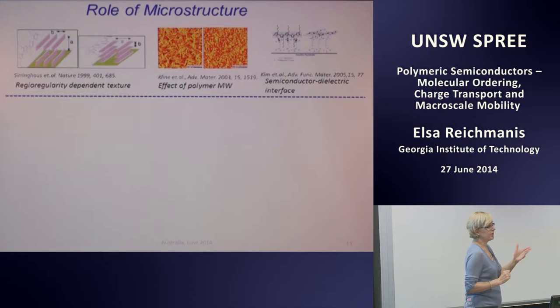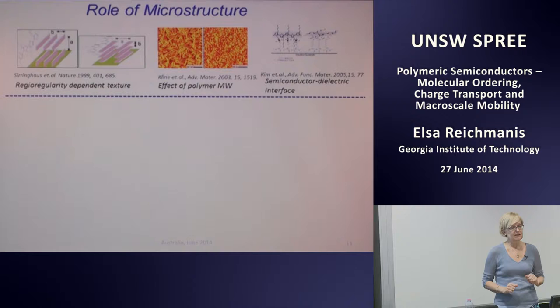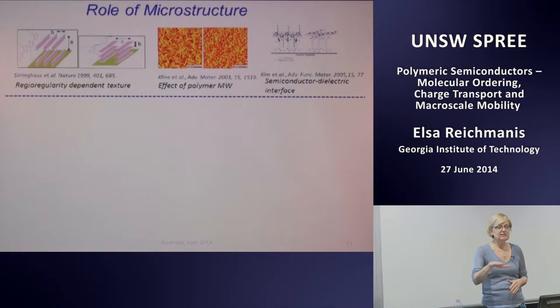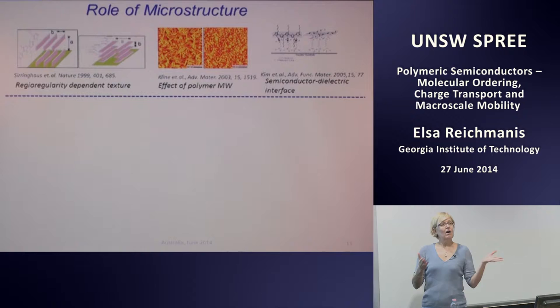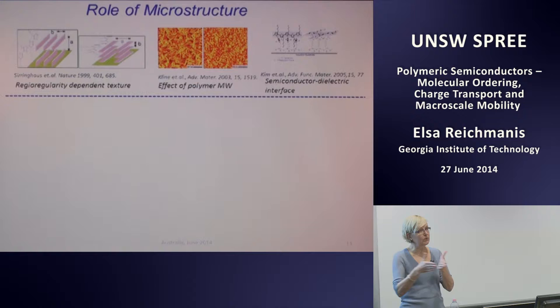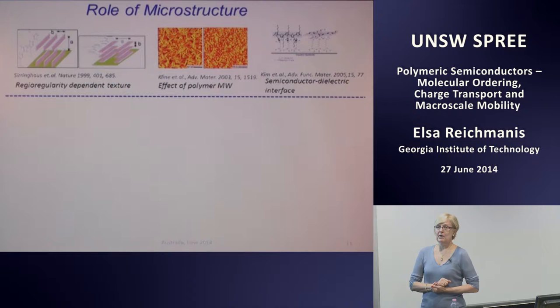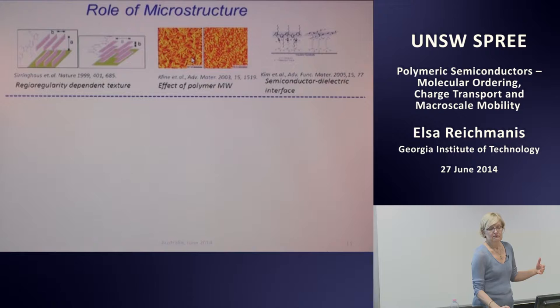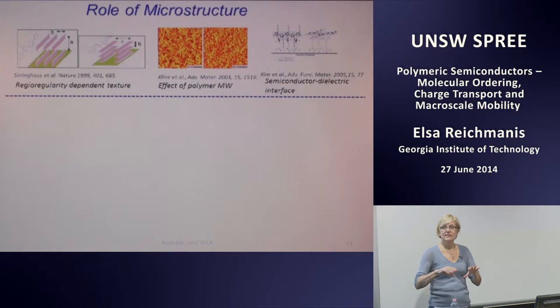A very regioregular material typically will lie perpendicular to the device substrate. One that is regiorandom will lie more flat on the substrate. And partly this difference in orientation determines how effectively charge gets transported through the film from one electrode to the other. The molecular weight of the polymer makes a difference. Kline and his co-workers showed that low molecular weight material, while it may be very crystalline on the substrate after deposition, has a much lower mobility than higher molecular weight material that is more amorphous in nature.